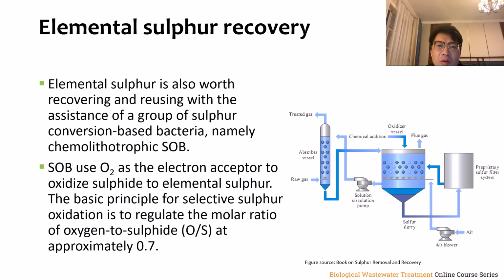A fundamental aspect of this control is maintaining the molar ratio of oxygen to sulfide, commonly referred to as the O to S ratio. For optimal results, this O/S ratio should be approximately 0.7. This precise regulation ensures that the sulfur oxidation process is efficient and that the maximum amount of elemental sulfur is recovered for reuse. By adopting such biotechnological processes, industries can reduce waste and enhance their sustainability profile.